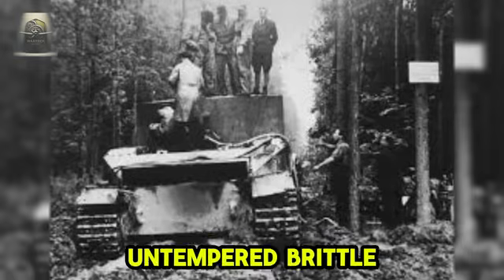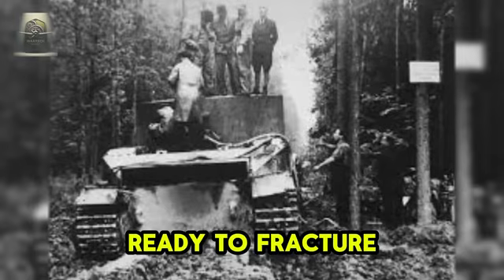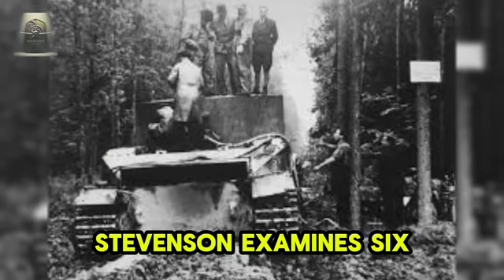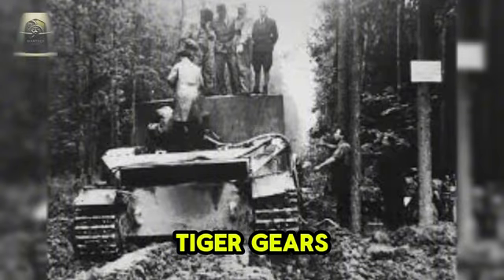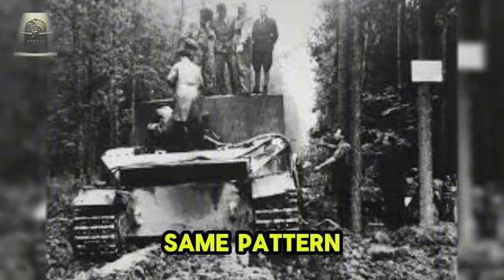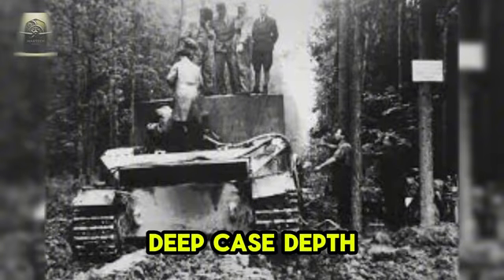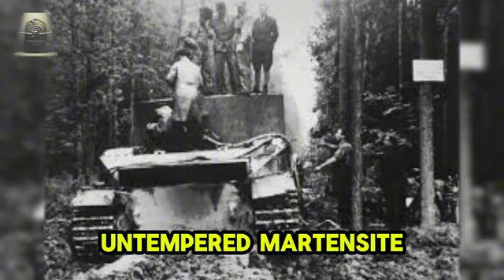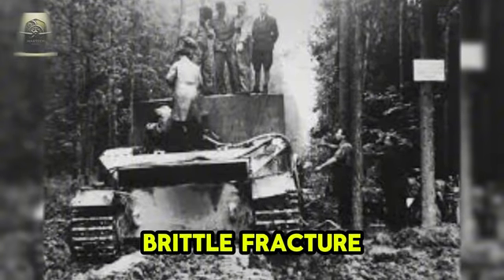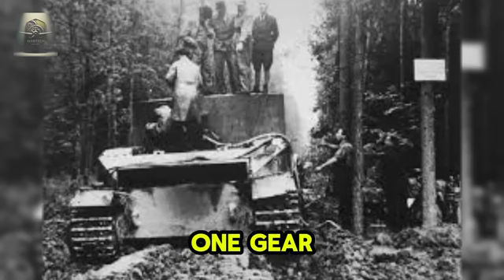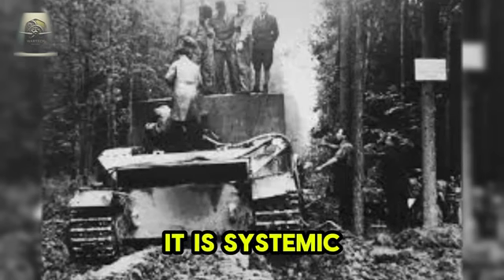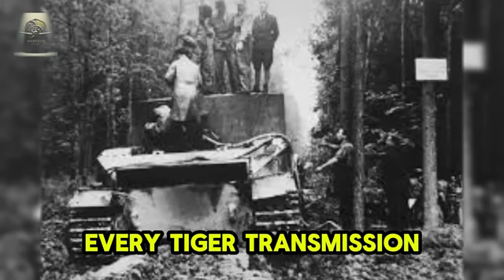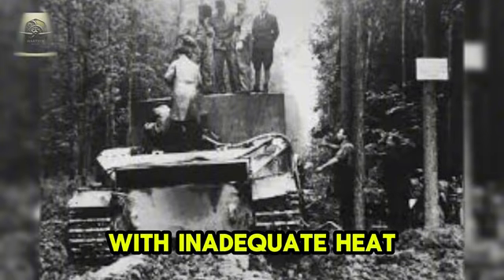The martensite is untempered, brittle, ready to fracture. Stevenson examines 6 more failed Tiger gears. All show the same pattern: excessive surface hardness, deep case depth. Untempered martensite, brittle fracture. The problem is not isolated to one gear or one transmission. It is systemic. Every Tiger transmission uses gears with inadequate heat treatment.